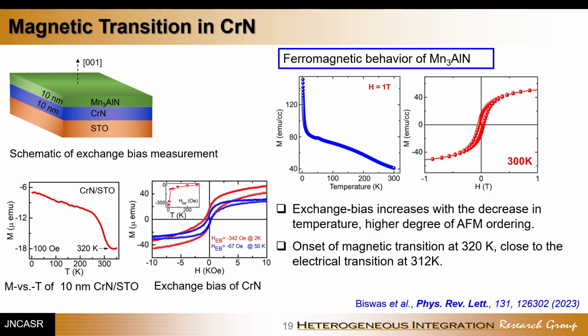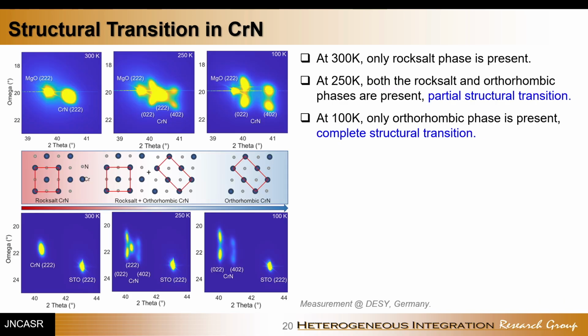We also did exchange bias measurement to show that the low temperature phase is indeed an antiferromagnet, and the amount of antiferromagnetic coupling, basically the exchange bias, increases as you go to lower temperature. So having shown the structure, electrical transition and magnetic transition, we also demonstrated structural transition. As you can see at high temperature, this is MgO and this is the chromium nitride peaks.